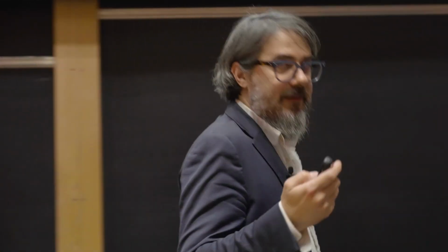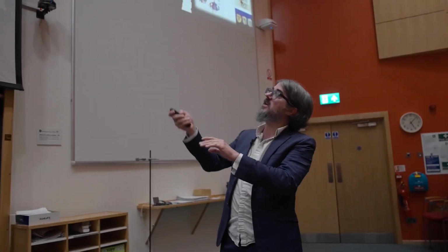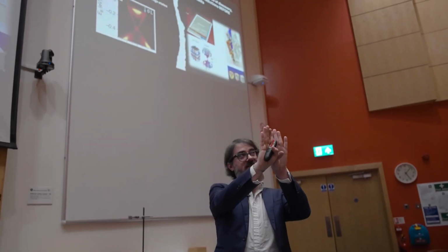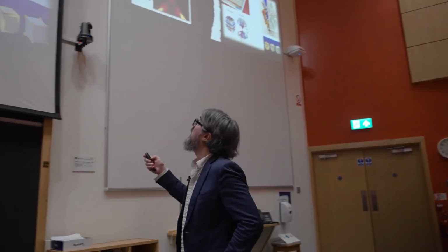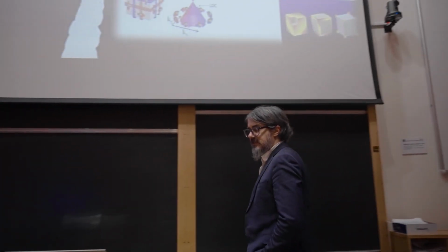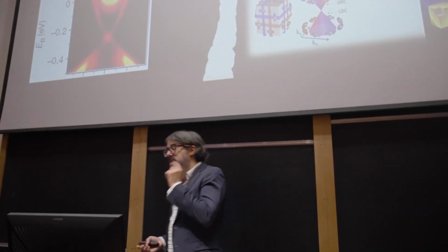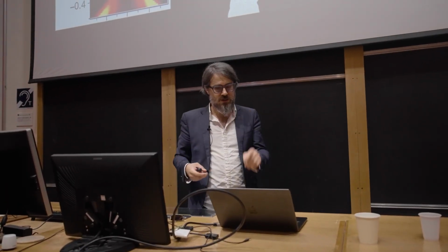Now, there's now many more examples. For example, this is an artist's rendition of bismuth, but bismuth, at least to the best of our experimental knowledge today, has edge states on hinges, rather, so it's a three-dimensional material. It doesn't have surface states on surfaces, but it's at the intersection of two surfaces, which are hinges. It has these electronic states. Now, the reason for that is because it's also described by a topological integer.